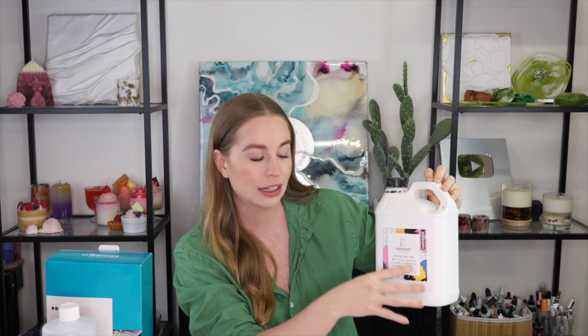This one has 40 minutes, this one has got like a longer 2-hour working time or 90-minute working time, and then from there you've got your curing time. So some can have, super fast setting resins can have a 3-hour curing time, some can have 12 hours, 48 hours, and those are just important things to look at, and that will depend on the projects that you're doing. But generally, when it has a really long working time, it means that it's a more fluid viscosity resin, which then allows me to do other techniques. And when I learnt that not all casting resins were the same, you can pick different types of casting resins for different techniques you want to create, that completely changed how I made pieces, understanding that.